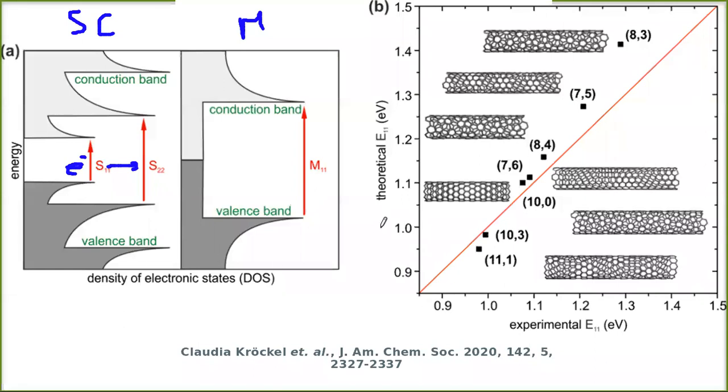So we could get a very nice picture from the experimental electron concentration, the experimental energy from this transition, and that will compare to the theoretical energy level that each of them is related to different carbon nanotubes, that they have different diameters, that they have different chiralities, and then all of them fall into this line because now our experimental result tells us that we cross the Fermi energy level of each of them at exactly the same theoretical or expected energy transition from each Van Hove singularity.